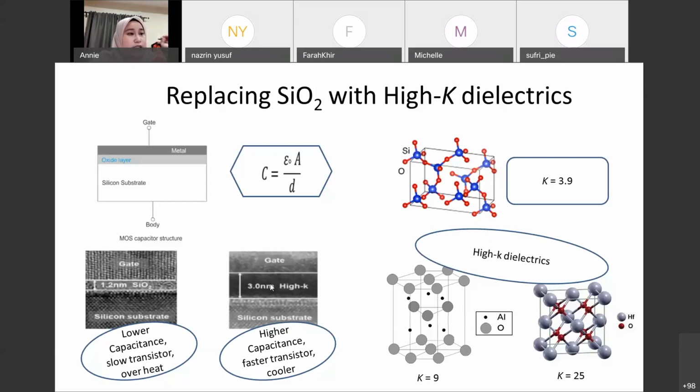Right, no problem. So what I got for the dielectric leakage current for this novel material: I managed to deposit an oxide layer down below 5 nanometer thickness. For that I managed to reduce the leakage current density of the novel material. So it's around 10^-6 to 10^-5 leakage density. So it's improved.